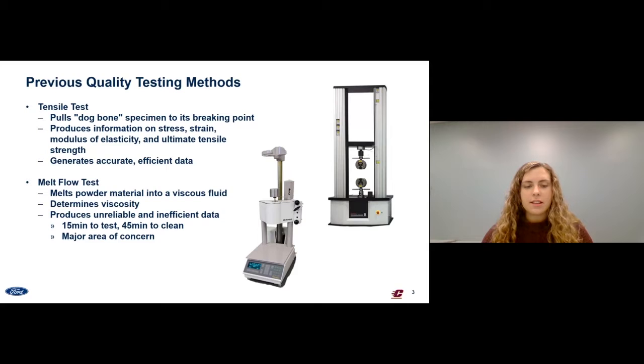The other quality test that Ford was using was a melt flow test. For this test, powder material is inserted into the top of the barrel of the machine, heated into a viscous fluid, then pushed out with a piston. This process has much more room for error than the tensile test, and our Ford contact mentioned that oftentimes the data collected is not used because he cannot be certain that it is accurate.